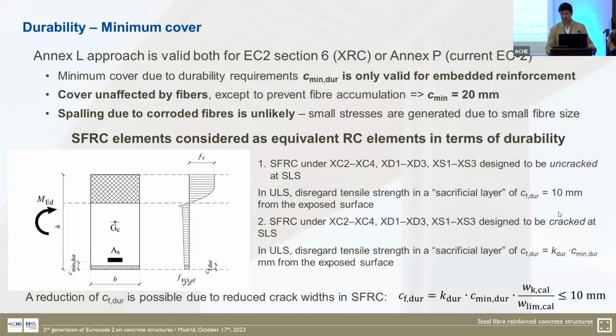In ultimate limit state, we can consider only 10 millimeters of concrete cover, and in case that cracking is expected or accepted in service limit state, we can accommodate this concrete cover with a reduction factor, which depends on the calculated and the limit value of the crack width.